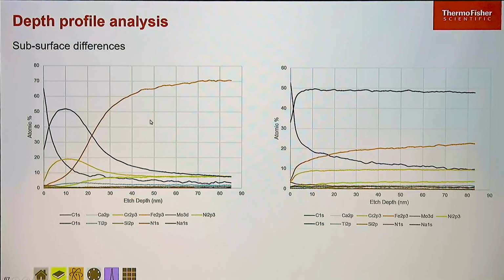So this is the profiles from the two steels. This is the good one over on this side. This is the bad one over here. And the first thing we can tell quite quickly is they're quite different. This line here that goes down, and this line here, that's the carbon being removed from the surface. As we remove the carbon, then we start to see other signals coming up. And on this sample, the signals we see coming up most quickly, and all these colors unfortunately look a bit the same on here, are chromium and oxygen. And so that's our passivation layer on the surface of this steel. However, over on this side, what we see coming up is actually the underlying components of the rest of the steel.